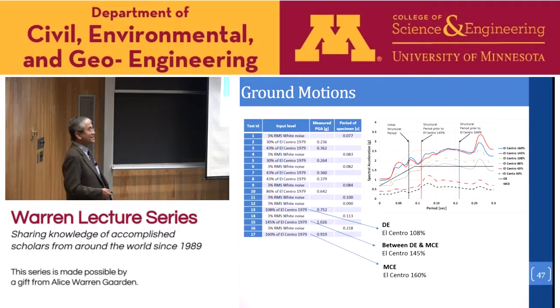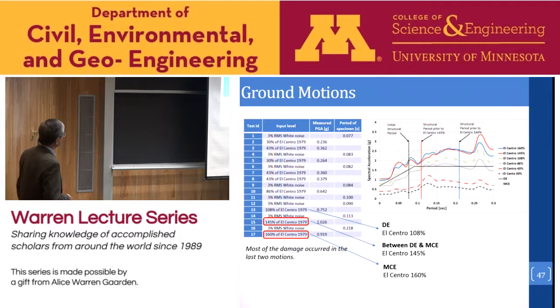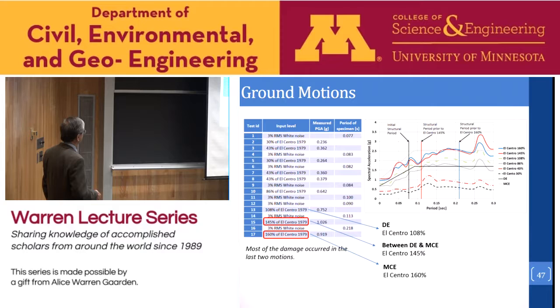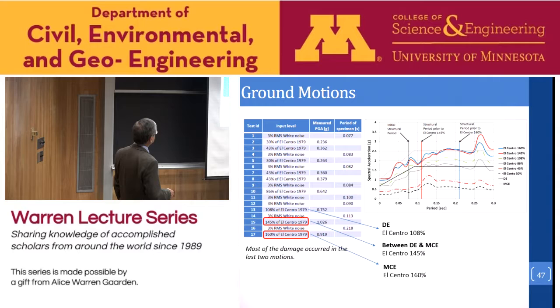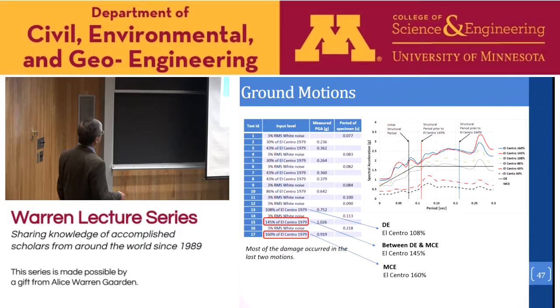However, the main damage occurred in the last two runs, at this run and this run. This run corresponds to the design and maximum considered earthquake, somewhat in between. The very last one corresponds to the maximum considered earthquake. You can see that initially this is the structural period. At this stage, there is a small period elongation because of some cracking and damage, but the damage was very minor. But after this run, you can see a significant jump in the period because of significant damage developed in the wall system. And this was the very final run.